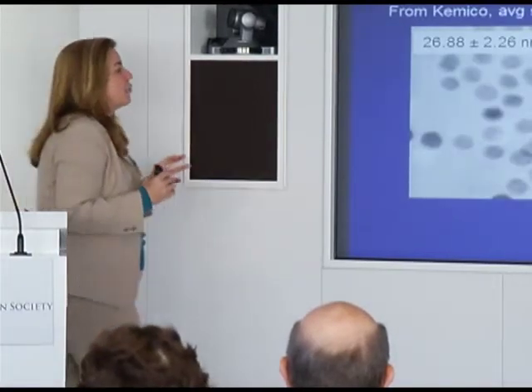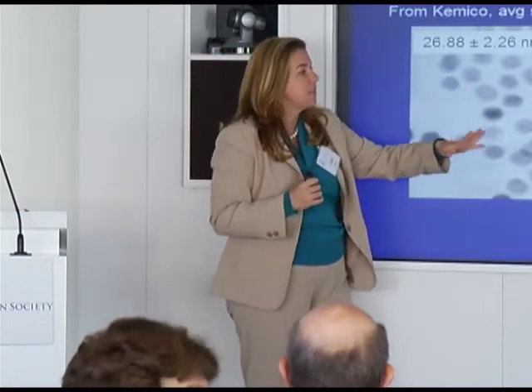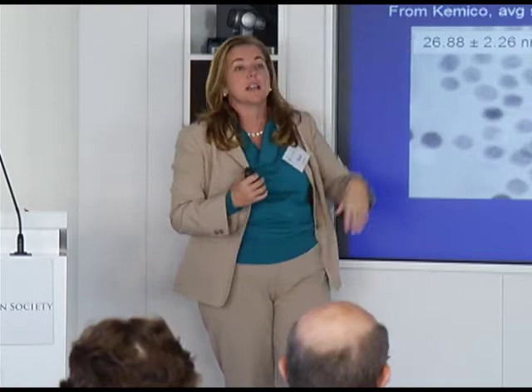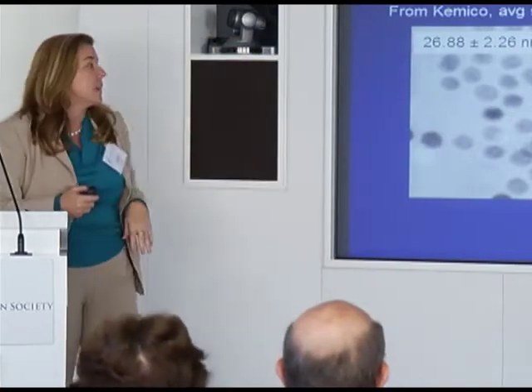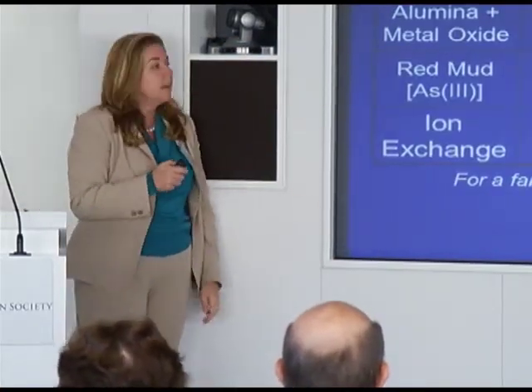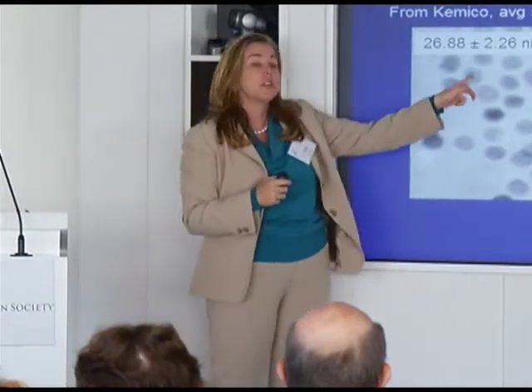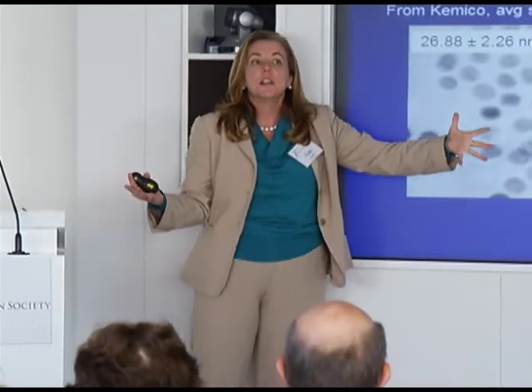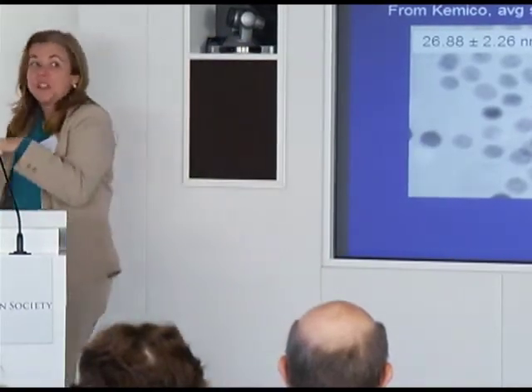So for other reasons, but these are examples of some of the materials that we would make, different sizes. This is actually commercial iron oxide sorbent. The difference between this example and these examples are two things. These are highly crystalline, and going back to that surface area thing, they have huge surface areas. So potentially we could trap a lot of arsenic onto the surface of the particles strictly by the surface area effect. So I worked with my environmental engineering colleague, Mason Thompson.